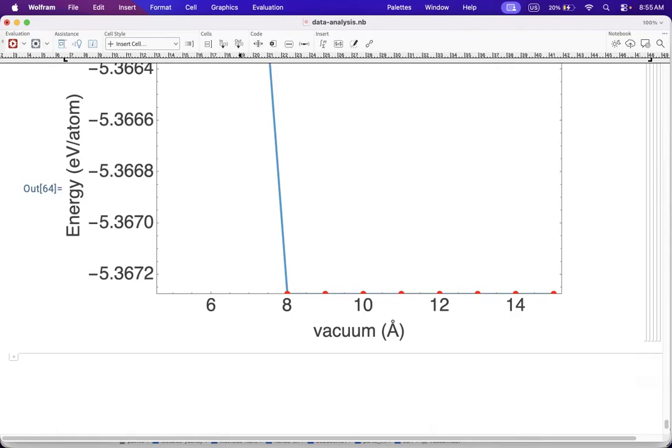So we can use from 8. In our case, we're going to use 11. Why? You could use 8, and you will find 11. Why? Because we want to simulate STM images. For STM images, we need an extra vacuum to study what is happening with the wave functions of the electrons in the vacuum. Okay, so anyway, is that clear, please? I'm going to stop here.